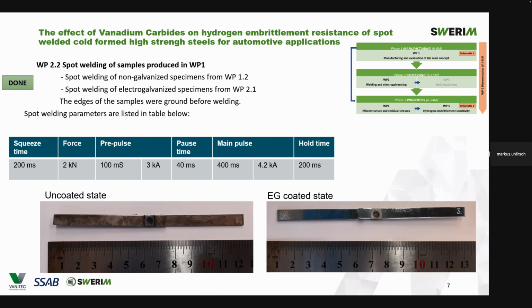When it comes to spot welding, we have done a lot of trials to optimize the spot welding parameters, and you can see the final ones in the table here. What's also worth mentioning is that the sheets we used for testing are quite smaller compared to the ones normally used, but still in those very small specimens we see a difference despite their small size. At the bottom, you can see two examples of spot welded samples: on the left, the uncoated state, and on the right, the electro-galvanized coated state.